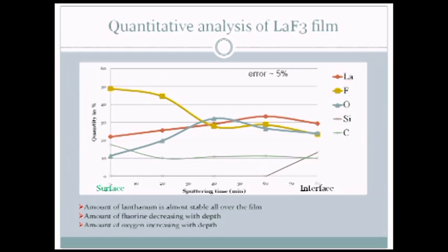Moreover, a quantitative analysis of the lanthanum fluoride film was made to understand the chemical composition, not only on the surface but all over the film. On the surface, as we can see, we've got more or less clean lanthanum fluoride. But if we go deeper, already in the middle of the film, we see quite high oxidation, which points us to lanthanum oxyfluoride, which has a different structure and different conductive parameters.